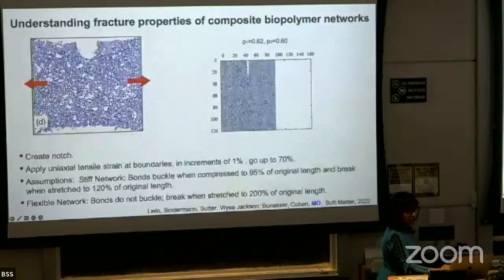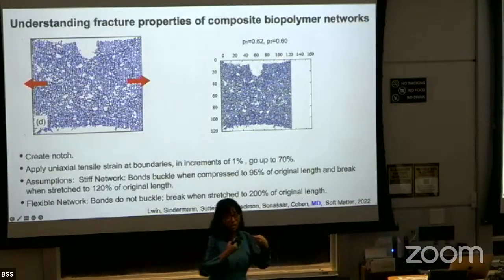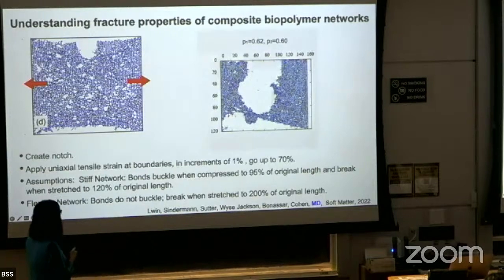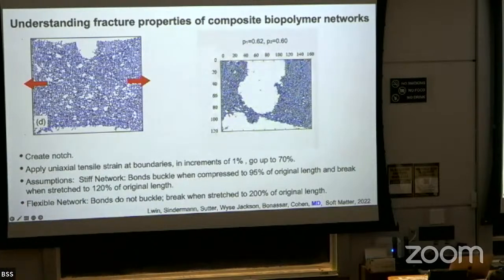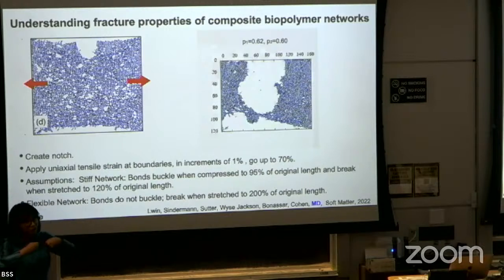So then you can ask what will happen if I look at large deformations, right? No longer just small deformations. So now we also create a notch to look at fracture. We apply uniaxial strain at the two boundaries, so no longer shear. And we start with 1%, and then we go all the way up to 70%, so really large deformations. And we make the assumption that for the stiff network, bonds are going to buckle if they're compressed to 95% of their original length or more, and they will break if they have been stretched to 120% of their original length. And when this happens, we basically just remove that bond from the network. It's not going to contribute anymore, right?